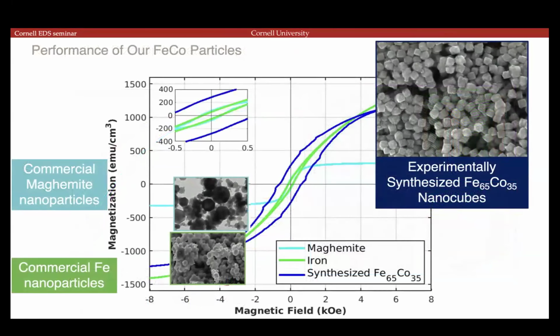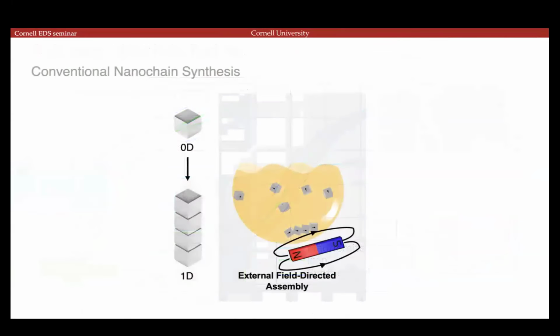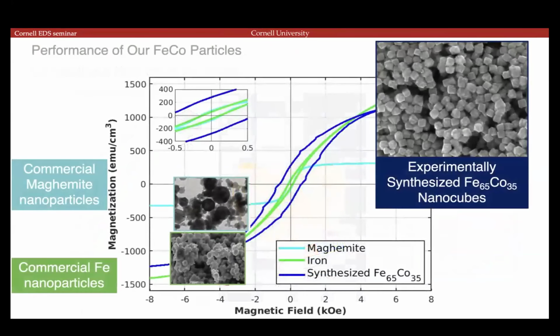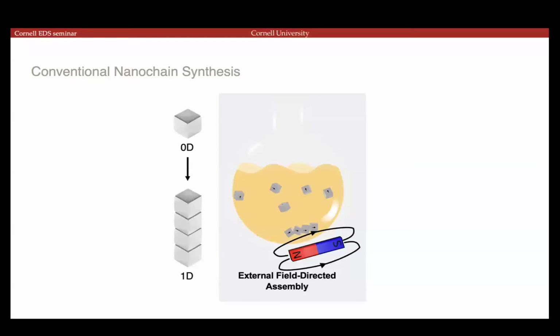So already just based on the single nanoparticle size, we can increase the remnant magnetization significantly compared to commercial nanoparticles, but we can still do better. So obviously there's still a lot left here on the table that we're not using. There's a huge portion of the magnetization that still remains to be had at zero field.